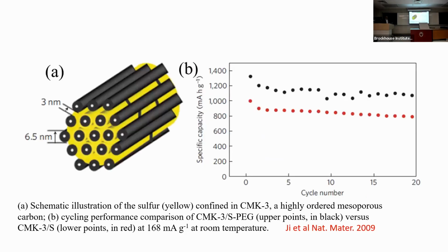I showed this paper because this was from a Canadian university, Waterloo. One thing they did is show that if you use a perfectly aligned carbon microstructure, created by some kind of template technology, and then infiltrate it with sulfur, this carbon structure remains intact. The path of sulfur going in, coming out and reforming is like entering a city whose map does not change.